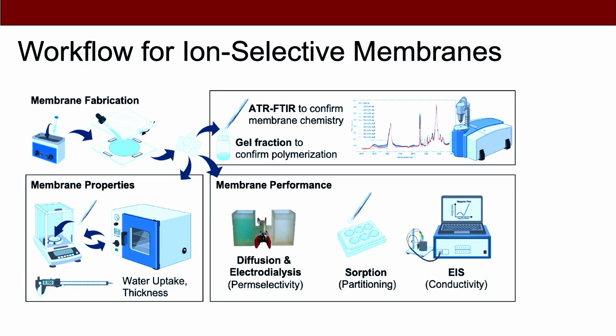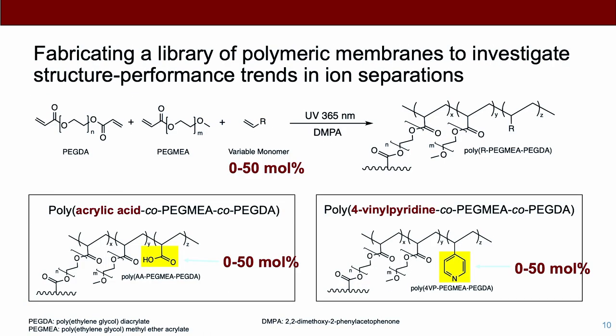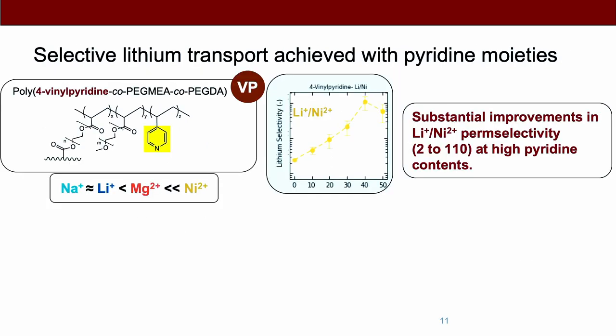I'll skip some of the details here, but in short, we have this workflow where we can use a polyethylene glycol backbone, and we can introduce, just look at the highlights here, different pendant groups, basically, right? And so we can just change out this pendant group and change the amount of it and try to screen for selectivity. So we're interested, being who we are, in some very fundamental design rules about if someone asked me to separate lithium from nickel, how would I go about designing that membrane in the most promising way? But along the way, we found a really promising membrane.